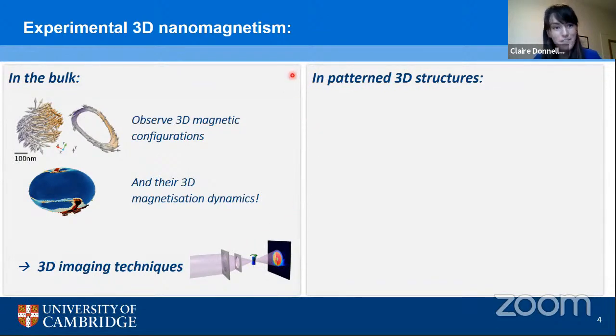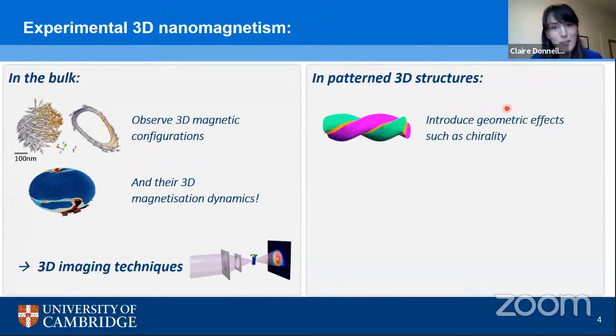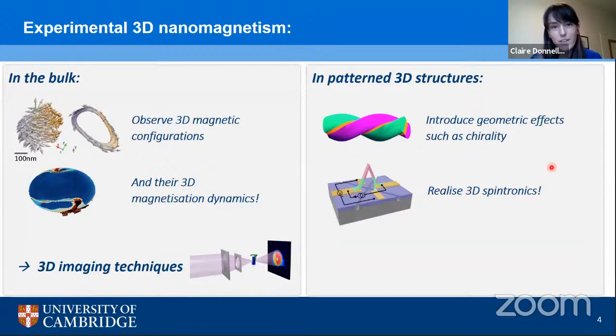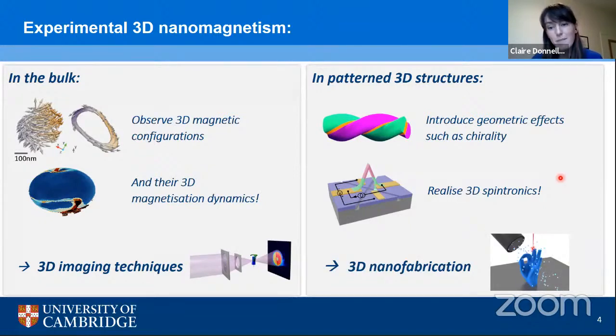Now, the second regime is the opposite extreme. As opposed to the bulk, where we're looking at magnetic structures almost in their natural environment, in patterned 3D structures we purposefully confine the magnetization by patterning magnetic materials on the nanoscale. And therefore, we're able to control or tailor the magnetic properties. Now, in 3D, this gives us a number of possibilities for new properties, for example by introducing new geometric effects such as magnetochirality, as well as taking a first step towards 3D spintronic devices. And again, in order to realize these systems, we need new types of methods. And the method in particular that we would really need are essentially new 3D printing techniques to realize 3D magnetic nanostructures.